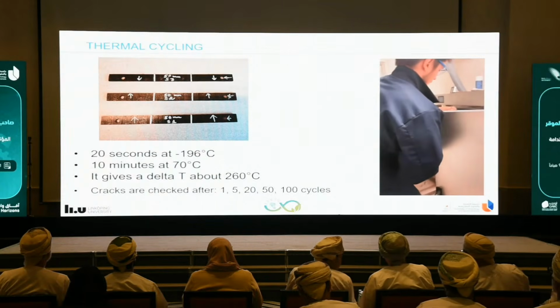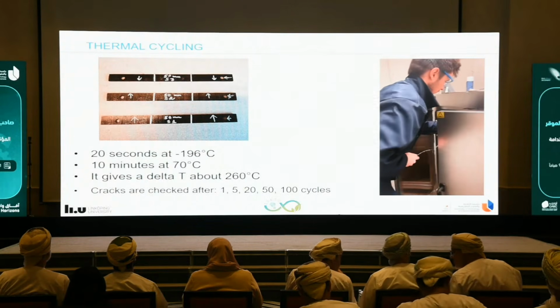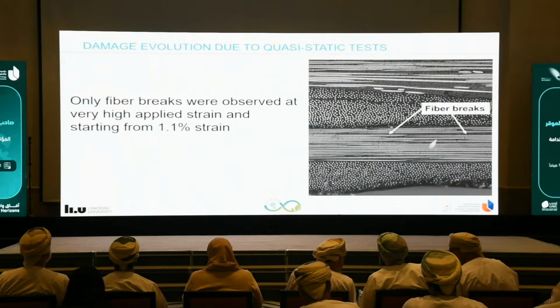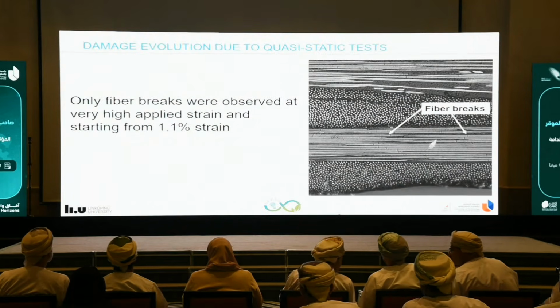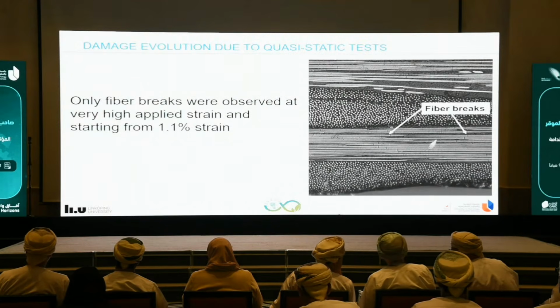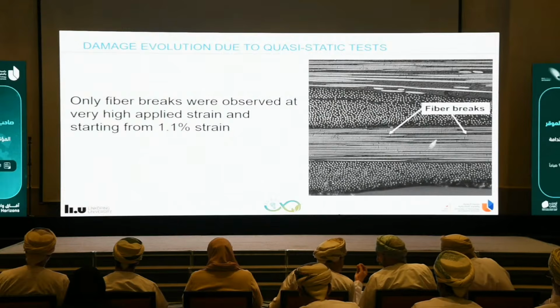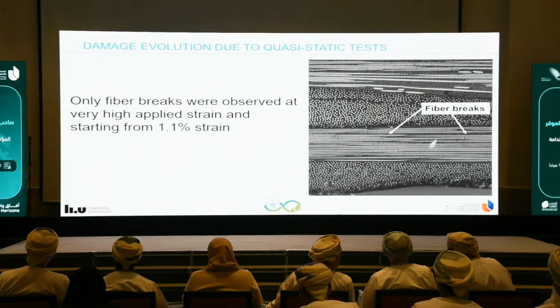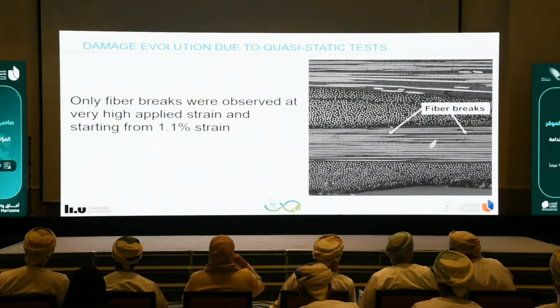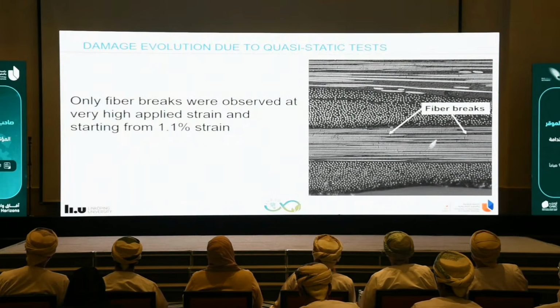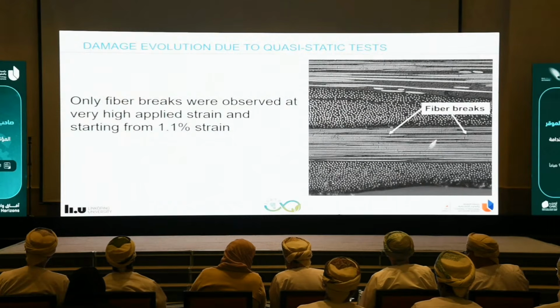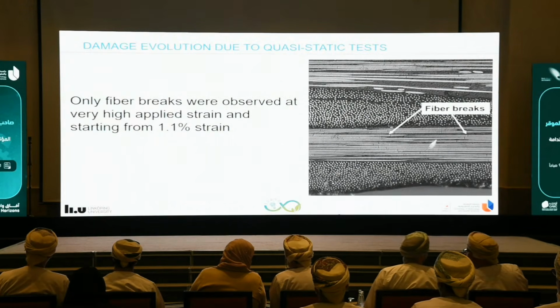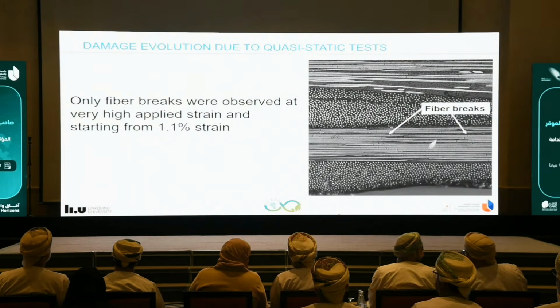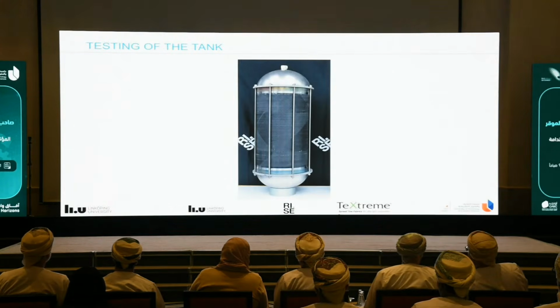And what we have seen is only some cracks in some layers. So we have seen some cracks, but it was only in some layers, which means that the hydrogen will not be able to propagate from the inner part to the surface of the tank. So the hydrogen will be stored there, since the cracks that we have seen are only in a few layers. So the hydrogen will not find the whole path to outside. So there will not be any leakage if we use this material. And this is the tank that we have made.